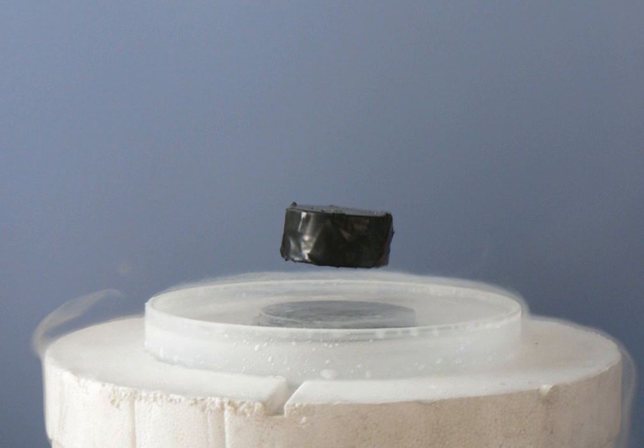Phase transition: In superconducting materials, the characteristics of superconductivity appear when the temperature T is lowered below a critical temperature Tc. The value of this critical temperature varies from material to material. Conventional superconductors usually have critical temperatures ranging from around 20K to less than 1K. Solid mercury, for example, has a critical temperature of 4.2K. As of 2015, the highest critical temperature found for a conventional superconductor is 203K for H3S, although high pressures of approximately 90 GPa were required. Cuprate superconductors can have much higher critical temperatures. YBa2Cu3O7, one of the first cuprate superconductors to be discovered, has a critical temperature of 92K, and mercury-based cuprates have been found with critical temperatures in excess of 130K. The explanation for these high critical temperatures remains unknown.